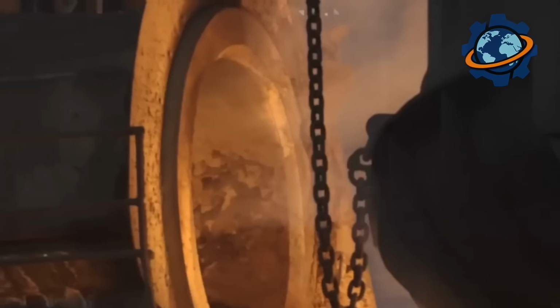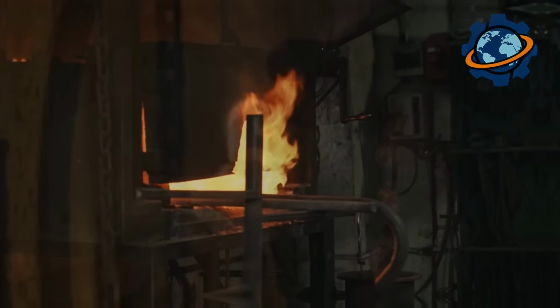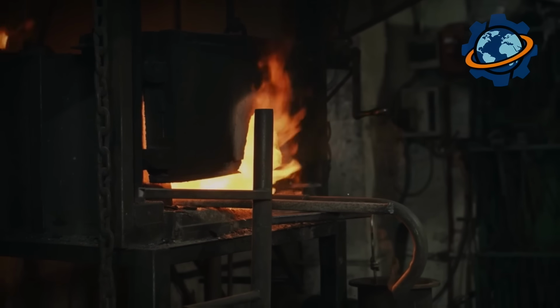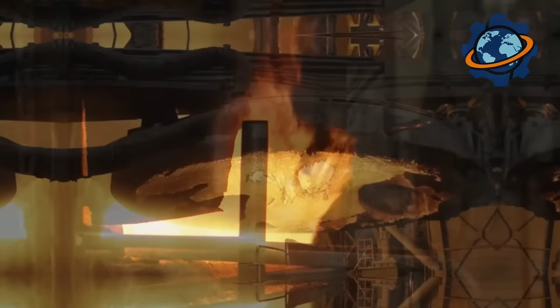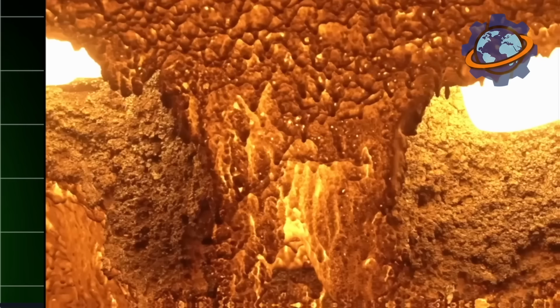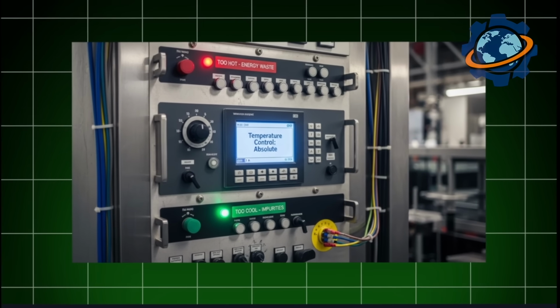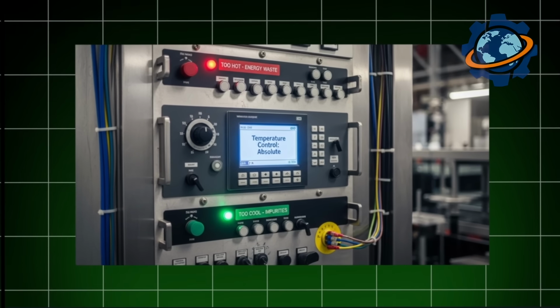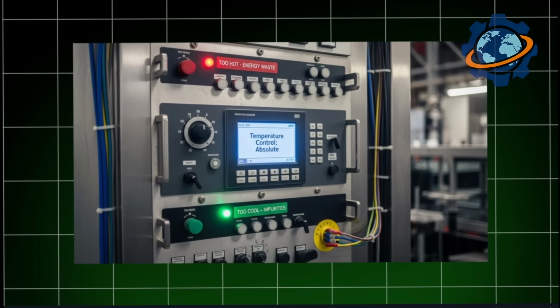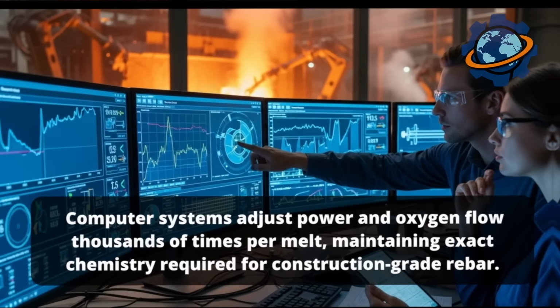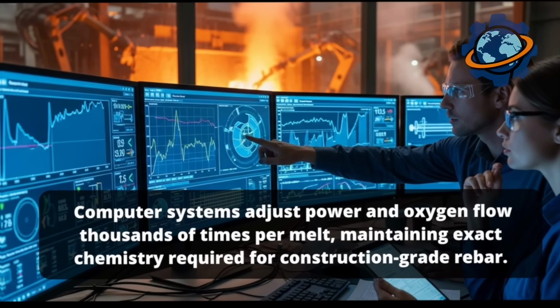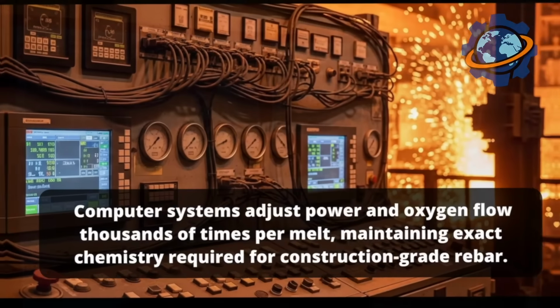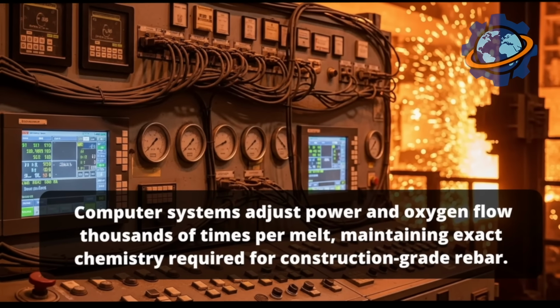Oxygen lances inject pure oxygen at supersonic speeds, burning impurities. Carbon oxidizes to gas, sulfur evaporates. Phosphorus combines with lime, forming slag that floats atop molten steel. Temperature control is absolute. Too hot wastes energy, too cool leaves impurities. Computer systems adjust power and oxygen flow thousands of times per melt, maintaining exact chemistry required for construction-grade rebar.